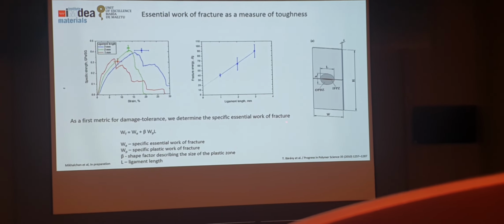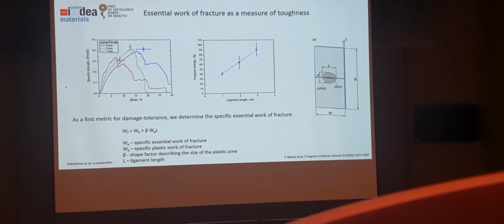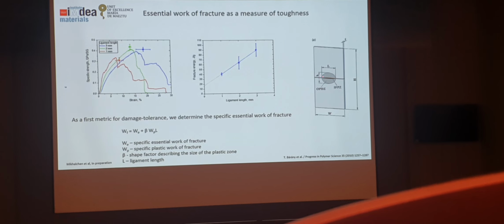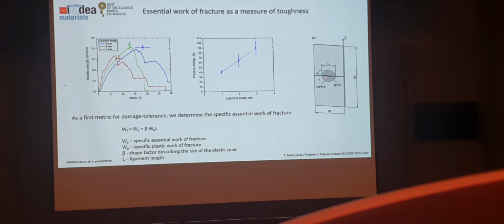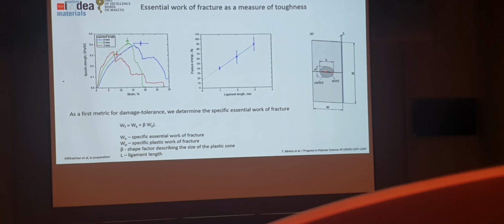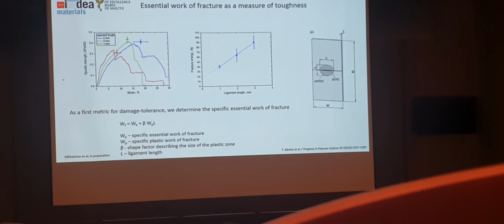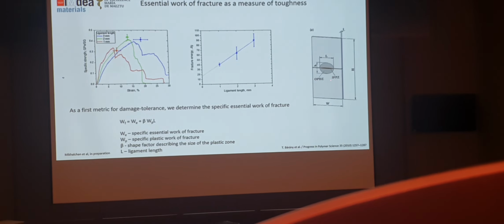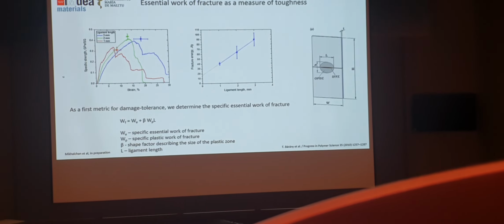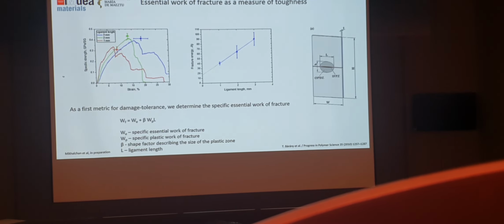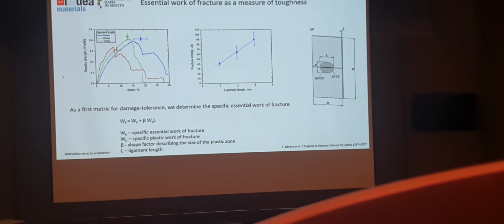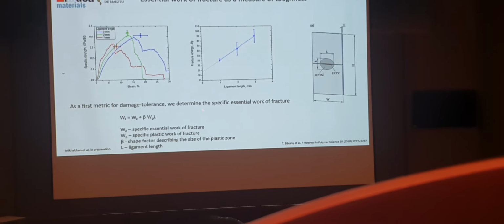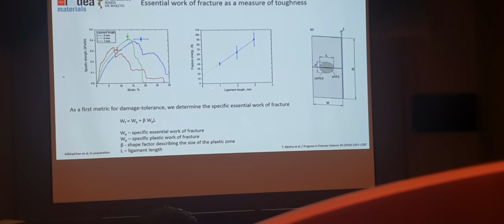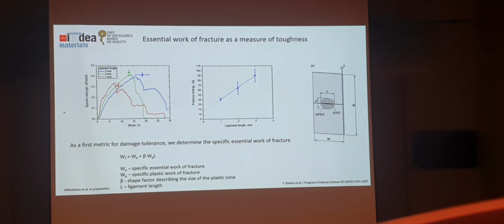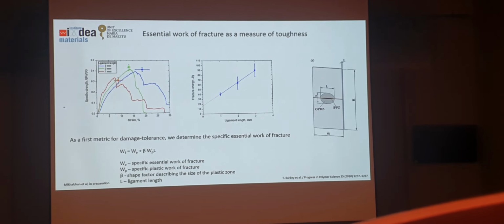Now, the whole idea is that if you do this experiment, the principle is that when the material deforms, there'll be an inner fracture process zone, which is related to the intrinsic or the essential work of fracture, and that will be a thin line. So that will depend on the length. And there'll be an outer area, the outer process dissipation zone, which may be really affected by the geometry of your sample. So that's how, for instance, ductile metals and plastics are analyzed. So it means that if you do this tensile test for different ligament lengths, you extrapolate to zero, you determine the essential work of fracture. So this is the simple equation describing that behavior. So you determine the essential work of fracture as the intercept, and you can also determine the plastic dissipation, which should be more geometry dependent.